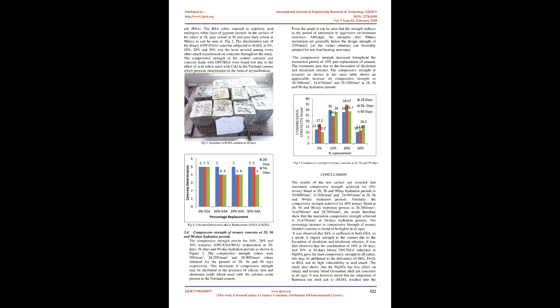The control concrete, i.e., OPC 0%, experienced moderate attack when exposed to 20% concentration of magnesium sulfate at 28 days. The attack was not severe compared to part replacement of GSA subjected to the same amount of acid.